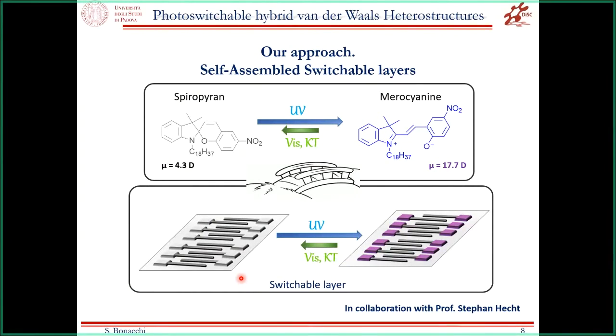In particular, what I would like to show you today is in this scenario, in this kind of research field, and also to do a step further. So not only to use a molecule to create a supramolecular assembled molecule to induce an effect on the electrical and optical properties of a 2D material, but the possibility to use switchable layer to switch in real time and in situ the properties of graphene or other kind of transition metal chalcogenide. And in particular, we select among different photoswitchable molecule, the spiropyran unit, and in collaboration with Professor Stephan Hecht at the Humboldt University of Berlin, we designed this spiropyran molecule with this long alkyl chain here, 18 C atoms, in order to induce a stronger van der Waals interaction among this alkyl chain in order to create a stable and stronger lattice on top of the material.